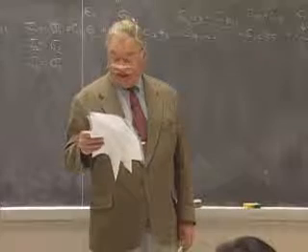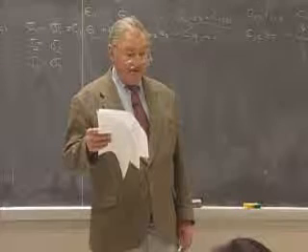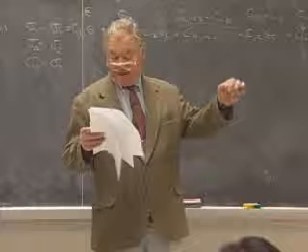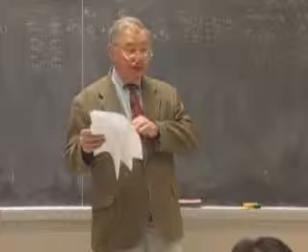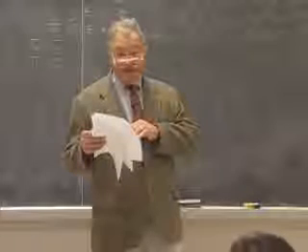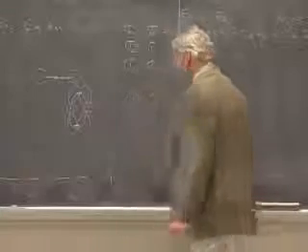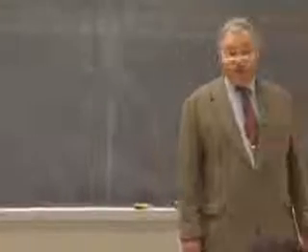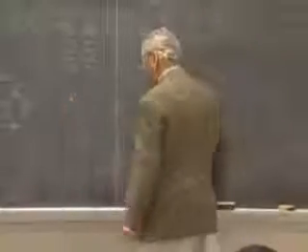Second assumption is that each atom is at a center of symmetry. And the reason for that is so the force in the plus x direction is the same as the force in the minus x direction. And that is not true for any material that has tetrahedral coordination. So it's not true for any of the forms of SiO2. It's not true for any of the compound semiconductors that are based on tetrahedral units. So there the atom inside of these tetrahedra is decidedly not at an inversion center.